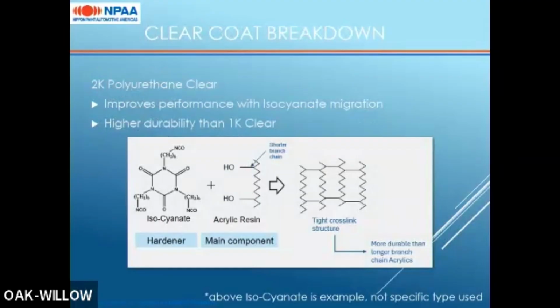And then the clear coat that we have for this system is a 2K polyurethane clear. Since this is a thin film build technology, 2K is generally the best way to go forward because it's going to offer better durability than a 1K clear coat. This improves performance with isocyanate migration. It's also higher durability than a 1K, as I said.